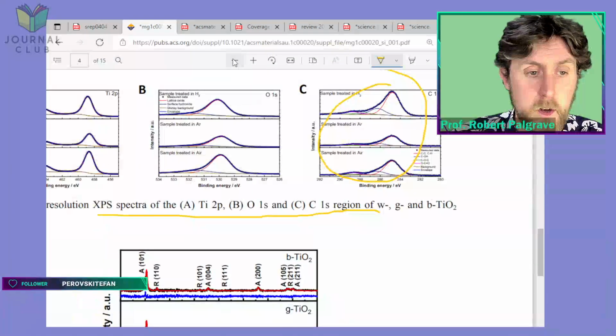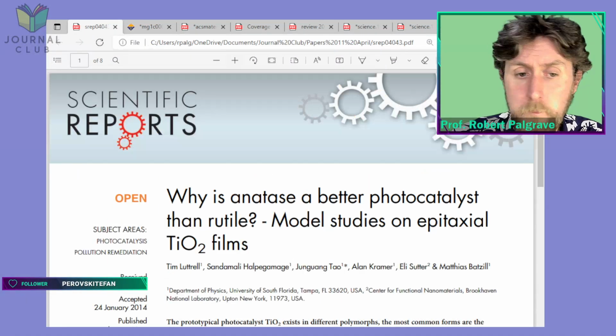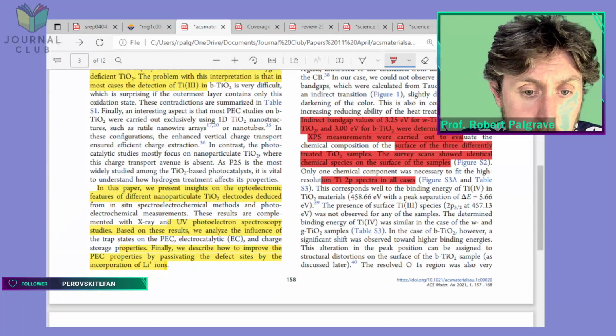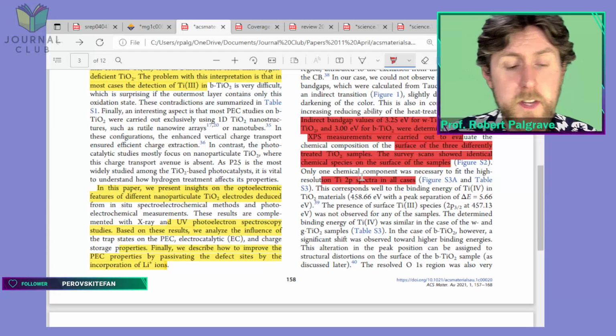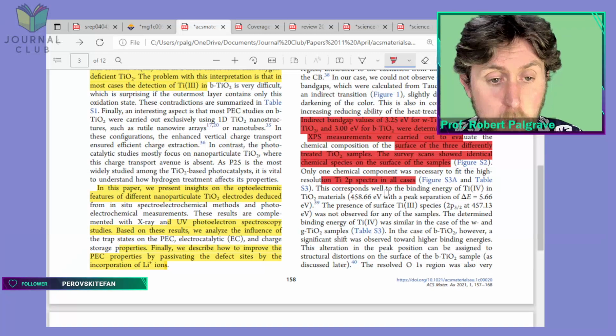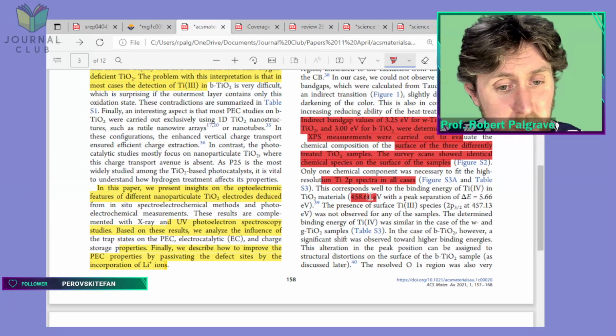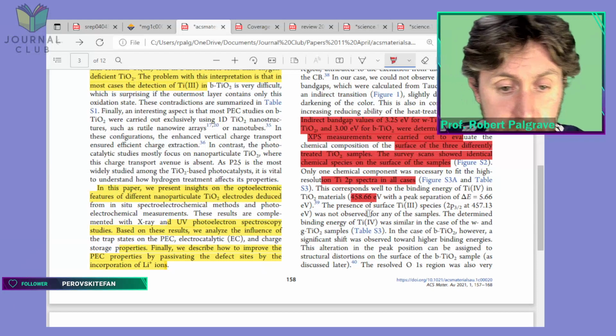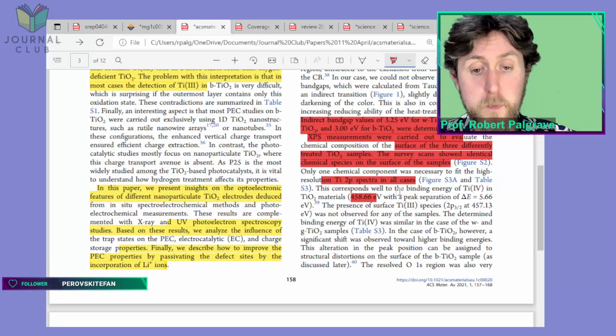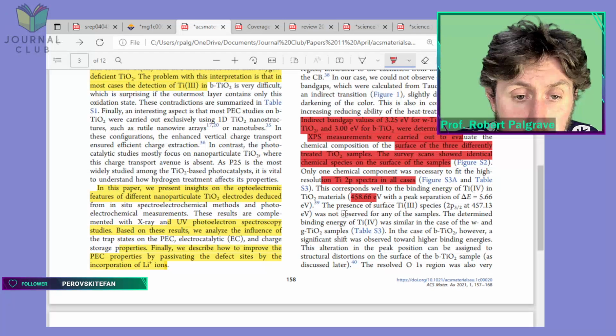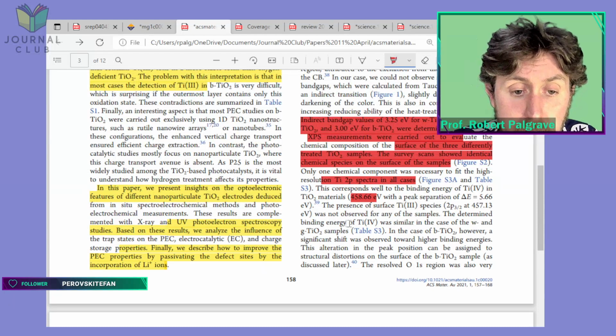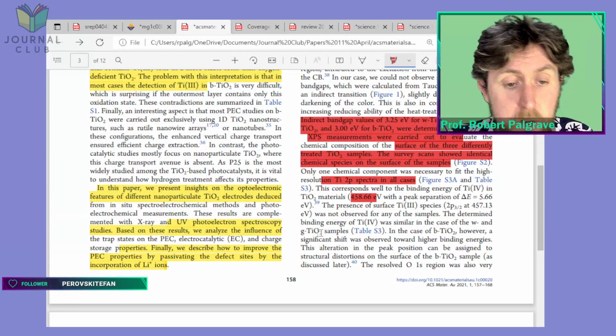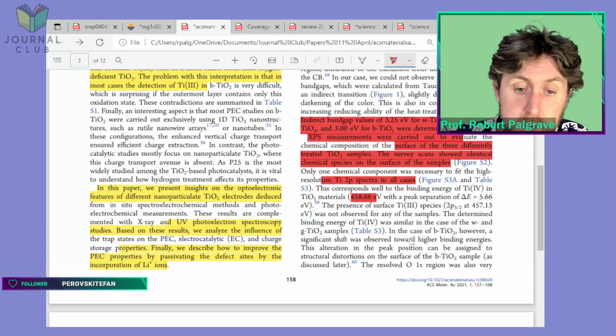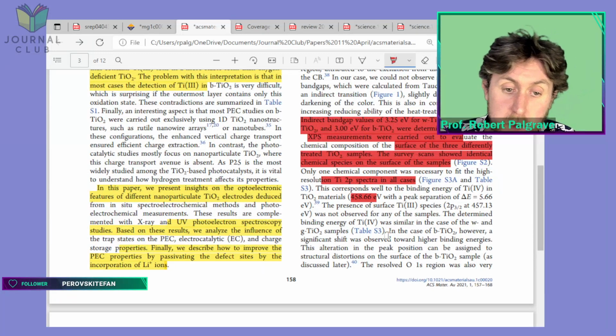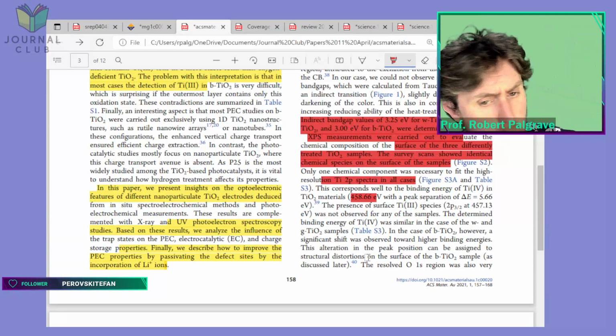Right, let me zoom out a little bit to get a better view here. That's the wrong paper. Here we go, back in the original paper again. So they showed the Ti 2p spectra. This corresponds well to the binding energy of titanium 4+ in TiO2 materials, and they're listing the binding energy to 2 decimal places, probably a little bit overkill on the accuracy there. And with a peak separation, they talk about the spin orbit peak. The presence of Ti3+ was not observed for any of the samples, as I just mentioned. The determined binding energy of the titanium 4+ was similar in the case of W and G samples, the white and the grey, but in the case of black, a significant shift was observed towards higher binding energies. This alteration in the peak position can be assigned to structural distortions on the surface of the black TiO2, as discussed later, I think. Maybe that's why.